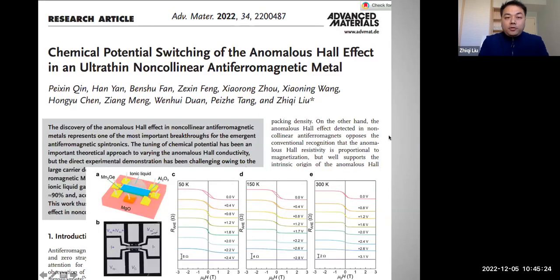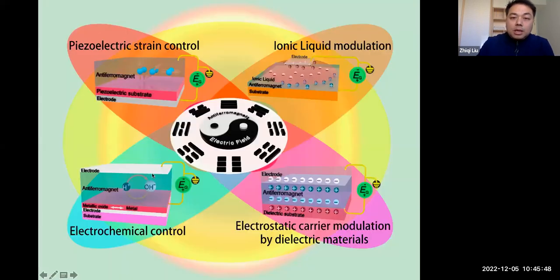So except for this piezoelectric strain control device, we can also use some other electric field approaches. For example, the ionic liquid. You can try to modulate the Fermi level of ultra thin antiferromagnetic metal, and then try to switch on and off the anomalous Hall conductivity. And also we tried to summarize all the possible electrical field approaches for controlling the antiferromagnetic spins. For example, we have piezoelectric strain, as I emphasized in this talk, and we can also have ionic liquid modulation.